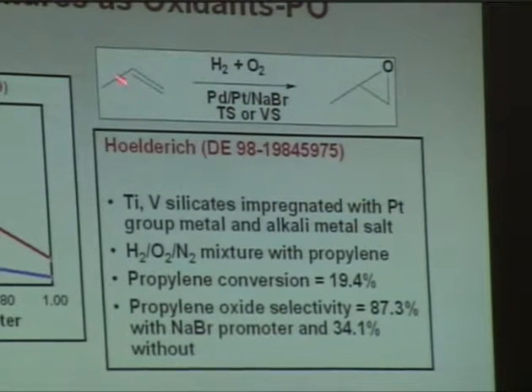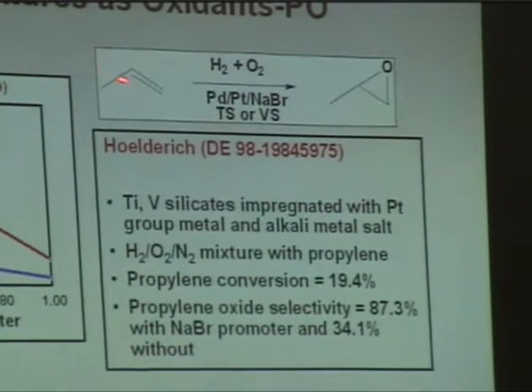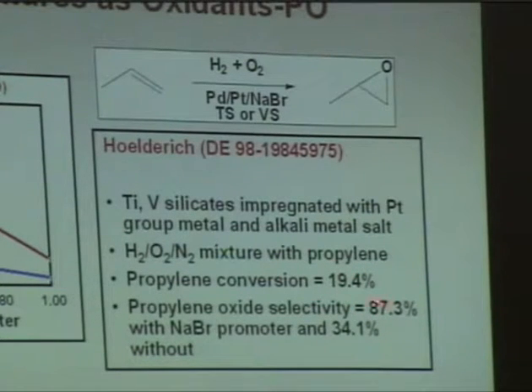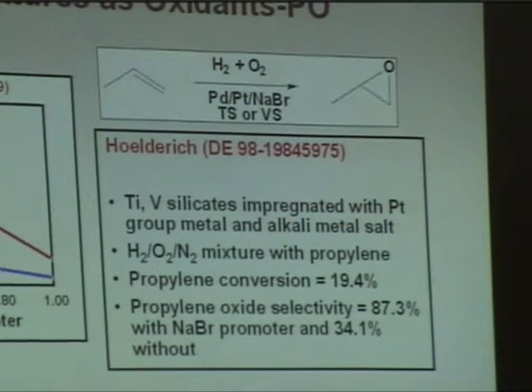And these are the results he got for directly converting propylene with hydrogen and oxygen to propylene oxide. 19% conversion and 87% selectivity to propylene oxide. This is a really remarkable reaction. And without the sodium bromide promoter, only 34% selectivity to propylene oxide. So this is an example, I think, of where we're headed in this area, using possibly hydrogen-oxygen mixtures instead of hydrogen peroxide. Safety will be an issue that everybody's going to have to learn to deal with.